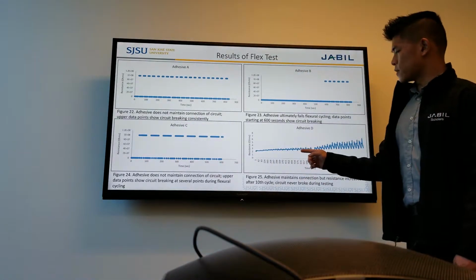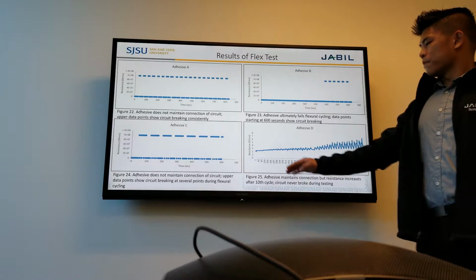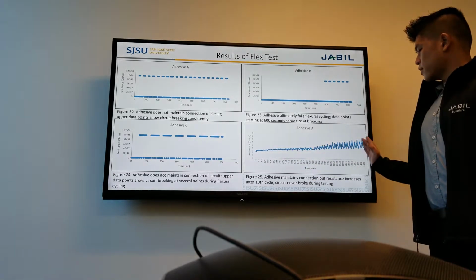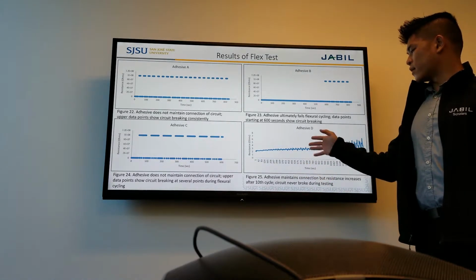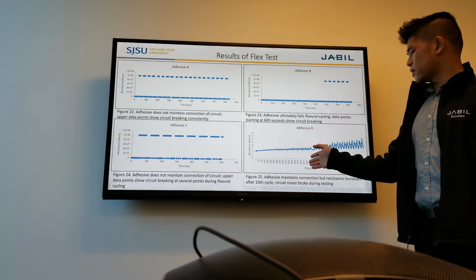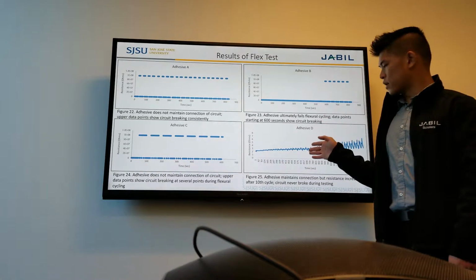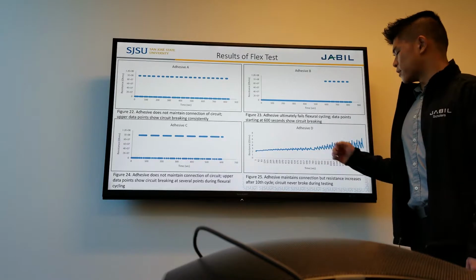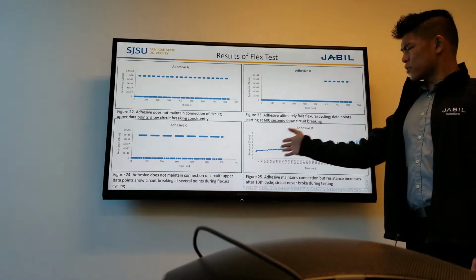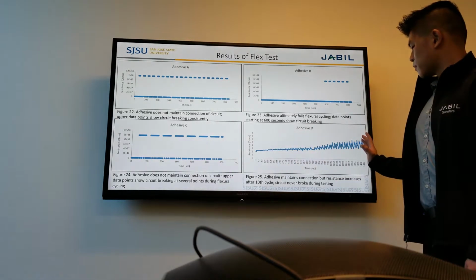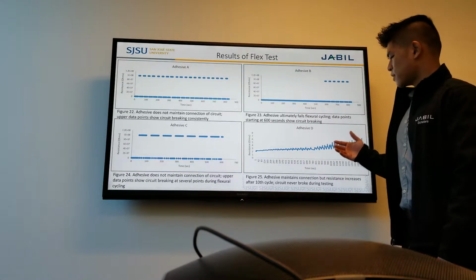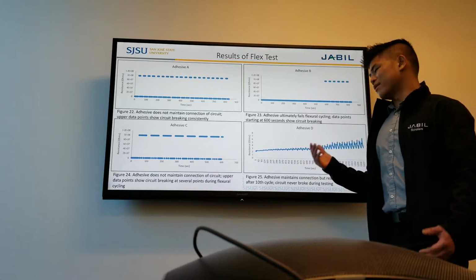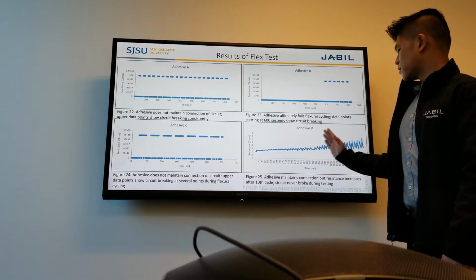Our most promising results were from adhesive D. Even though resistance increased dramatically, it did not break the circuit. And this is from extensive testing. Past 10 cycles, which is our maximum number of cycles actually, the circuit did fine. But after the 10th cycle, the resistance started to increase due to heat. The heat increases resistance, but normally you're not going to see that. This is just for durability testing.